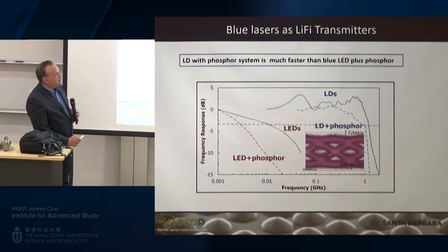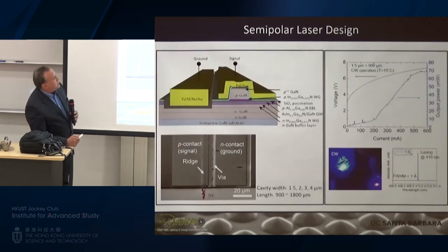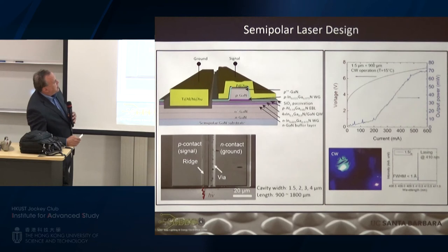I'd like to work with Patrick on laser Li-Fi because I think there's a lot of opportunity here now to push this forward. We pushed it forward by coming up with new laser designs where we shrink the ridge width down. This is one in which we shrink the ridge width down to 1.5 micron. That's the ridge width here, and what that's going to give us, as you can see, is faster speed. So we've gone with longer cavities, but very narrow in the lateral dimension.